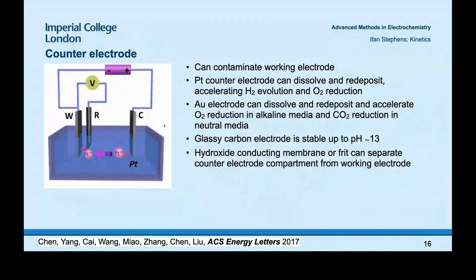An alternative would be to use gold. Gold is generally more inert and less catalytically active, especially in acid solutions. But even in alkaline media, gold can be very active, for example, for oxygen reduction, so using a gold counter electrode is not necessarily a good idea. Similarly, if you're doing CO2 reduction in neutral media, the gold can dissolve and redeposit at your working electrode, and gold is a pretty good catalyst for CO2 reduction to CO.